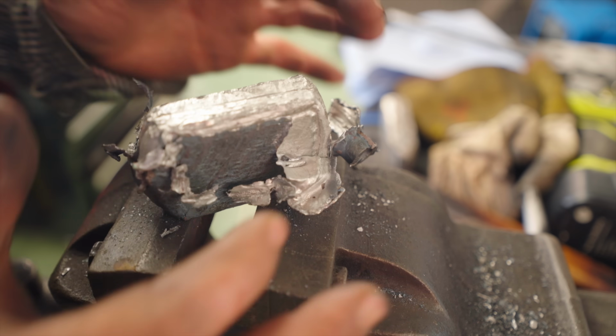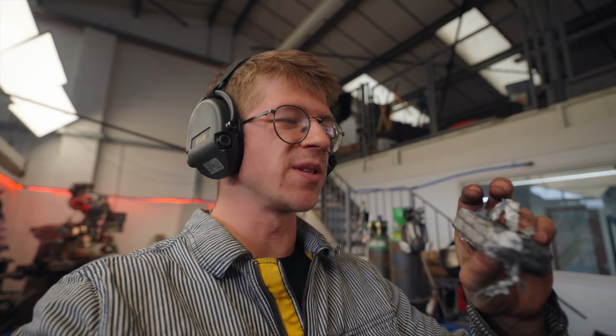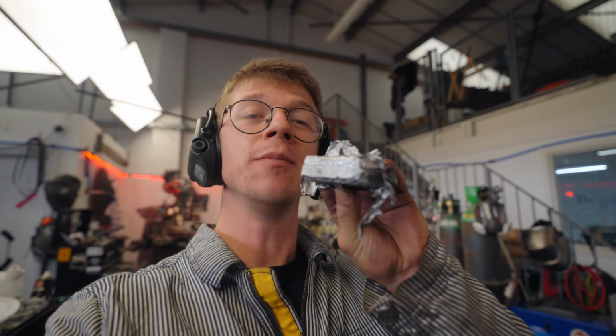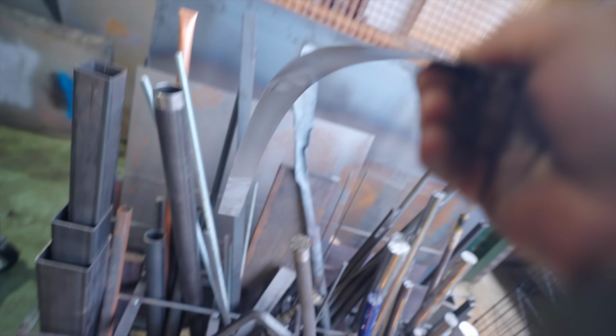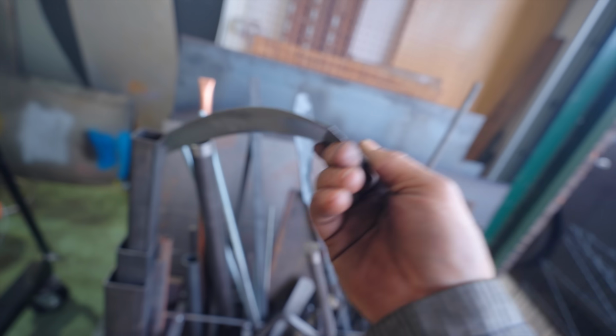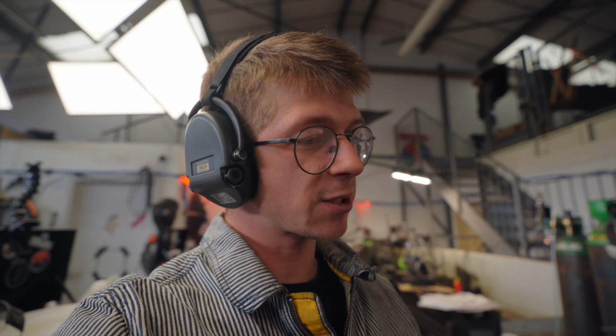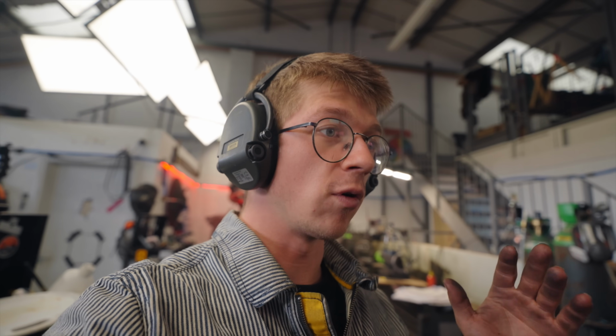Okay, this is a nightmare. This is taking about 10 times as much time as getting the 2 millimeter steel jacket off. So, I have found a definite no-no when making titanium Damascus. Don't make a jacket from super thin steel. 0.6 mil is too thin. 2 millimeters did work fine. I think the trick is going to be experiment with 1.5 millimeter.